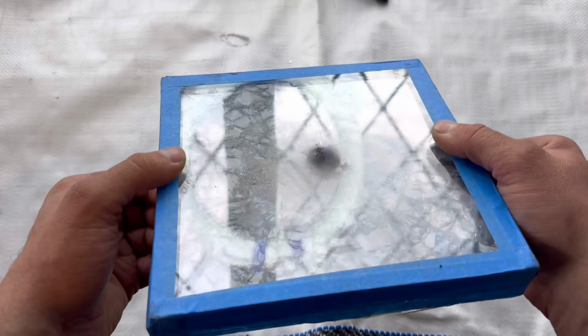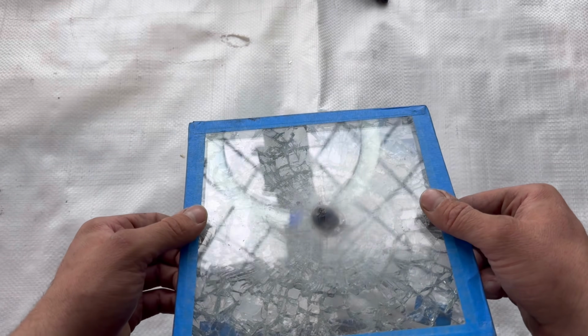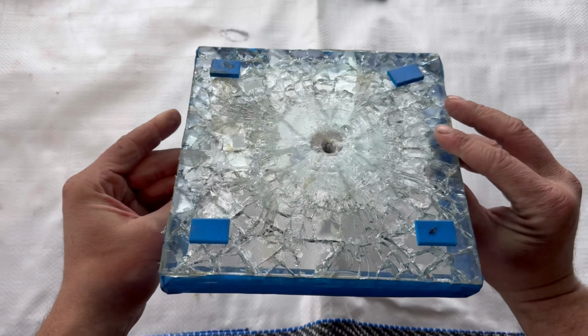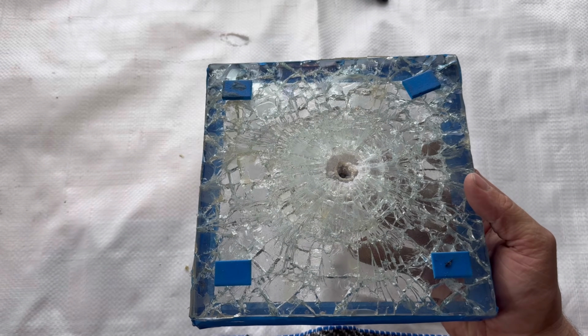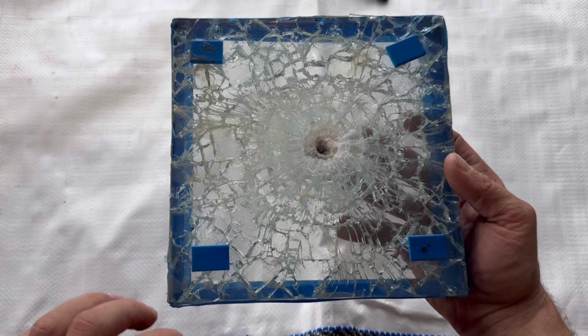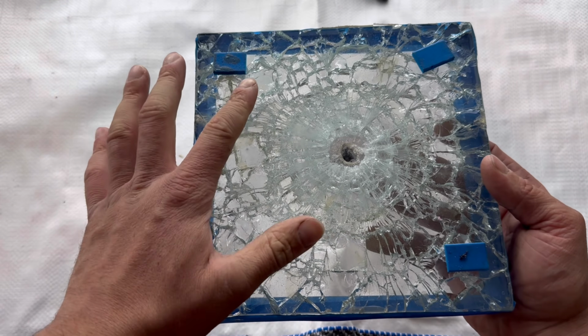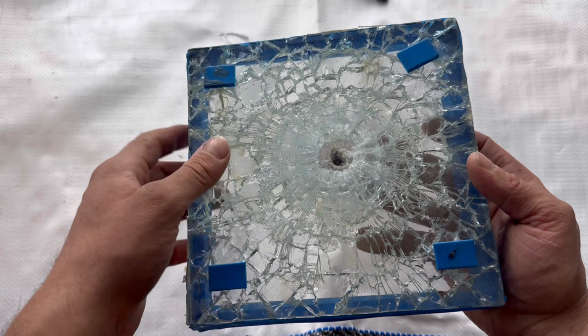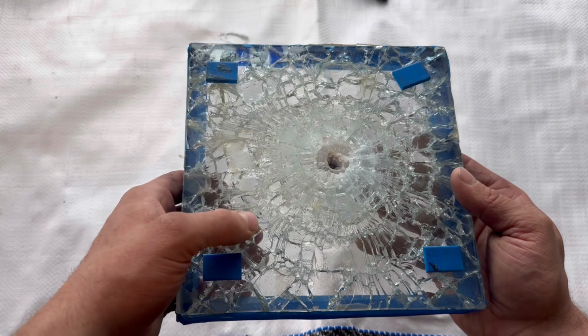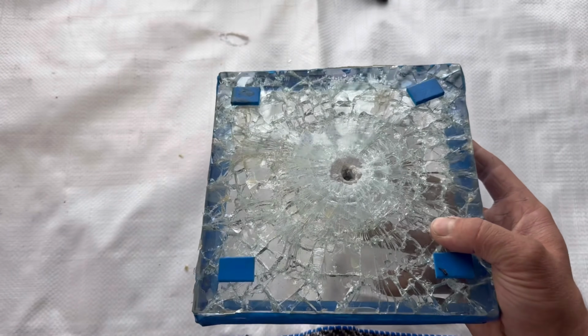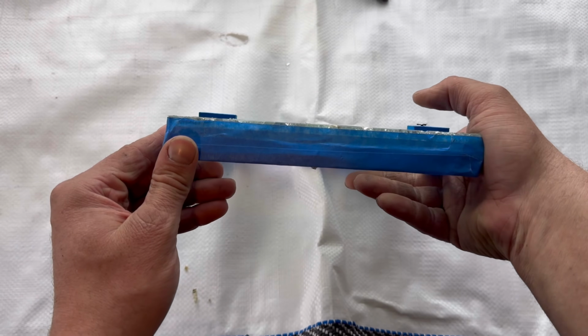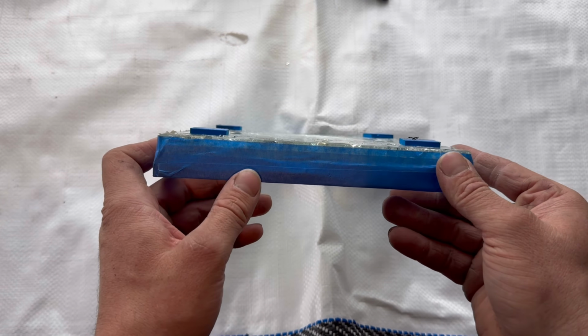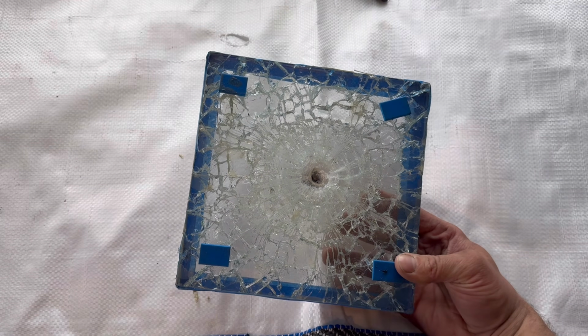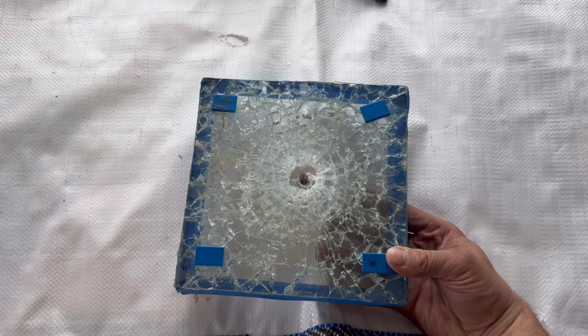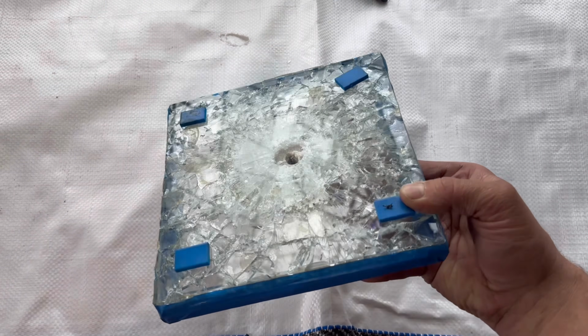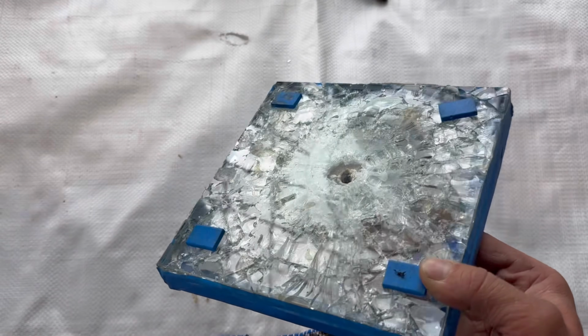So that is 2 layers of 10mm polycarbonate, fronted with 6mm of glass on the front, which I assume is a form of table glass, some form of toughened glass, especially with how it shattered. That softer resin as well largely kept hold of it all. Parts of it are falling out, but a lot of this is still actually glued to the polycarbonate. I don't think I can make the glass in the helmet, of course, 26mm thick. I think it's just going to end up being polycarbonate with some glass at the front of it. So it'll at least stop 22. But probably not 223 when it's in the helmet, or 556 for that matter.